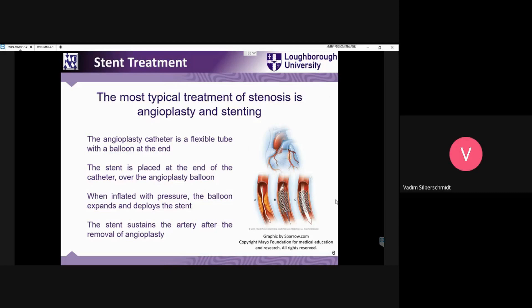For stenting, we put a stent on the end of this balloon, and we can deploy the stent inside the artery. Then, by removing the internal pressure of the balloon, we can leave a fully deployed stent. Clearly, we must overcome the elastic range of deformation so that there is a residual deformation of the stent inside the artery. Then we can remove the balloon out of the artery.